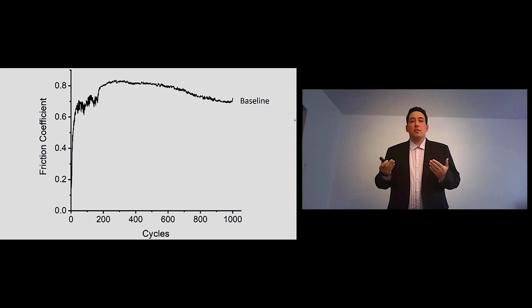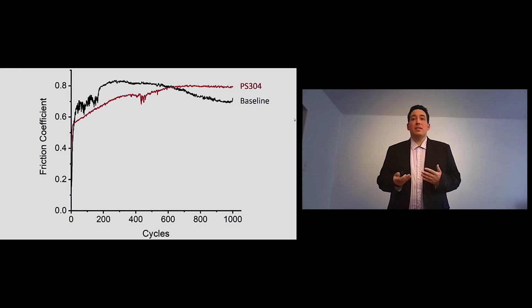Well, first, we test for the friction coefficient, which is a measurement of how much energy you're losing. In this case, the lower the friction coefficient, the better it is for energy consumption. It means that you're losing less energy. The baseline that you see is a material well known for us that is already being applied. When we tested the PS304, what we see is higher friction, especially at the end of the number of cycles that we ran. However, the PS304 showed really good results and really promising results for our application.